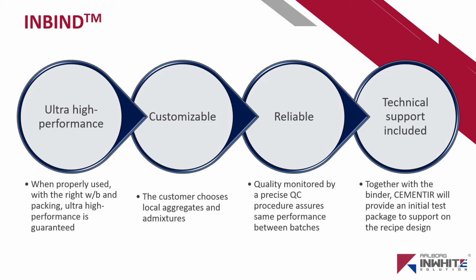If we must condense in one slide the main benefits of InBind, then this is the one. By using InBind with the right aggregates to ensure the maximum packing, and also with water to binder ratios between 0.21 and 0.27, ultra-high performance is guaranteed.